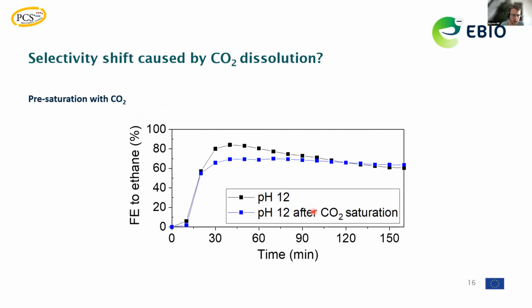So we were puzzled by what is the influence of the formed bicarbonate and carbonate ions on the process conditions. And to study this in more detail, we started off with a pre-saturated solution, where we intentionally purged CO2 before starting operation of the process. And what you could see at pH 12, we already obtained a low Faradaic efficiency to ethane, even at the beginning of the entire operation of the electrolysis.